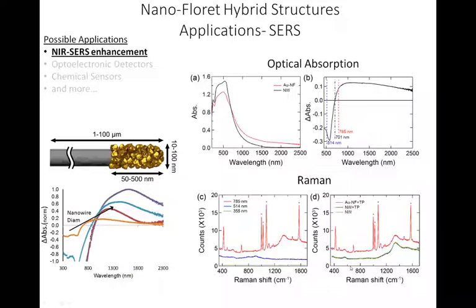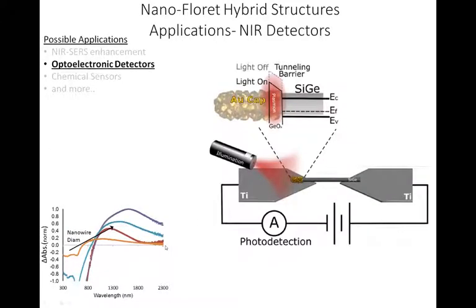And this was the opening to say if we have this near IR surface enhancement that we can use in Raman spectroscopy, why can't we simply use it, because it's already coupled to a semiconducting nanowire in an optoelectronic device. And this is exactly what we did. So we simply grew these silicon germanium nanowires on titanium electrodes that are tip structured, and those bridge between the gap here.